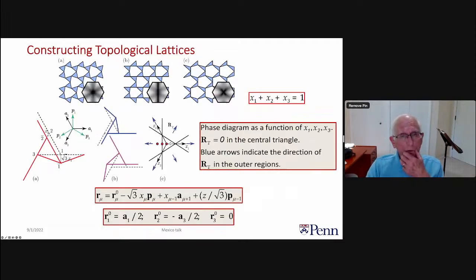Okay, so now we're going to get finally to topological things. So here is the twisted Kagome lattice, which we're going to call a non-topological lattice for reasons which will become apparent in a minute. Now we need to have some way of changing the topology, the properties. What we saw before is that if I twist all of the directions back to a Kagome lattice, we have straight lines going in all 3 symmetry directions. So we're going to simplify things so that we rotate these so we get a straight line of bonds along one direction only. So here is a critical point that separates the non-topological lattice from the topological lattice.